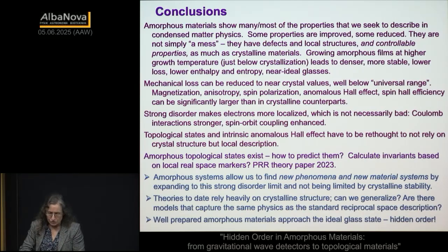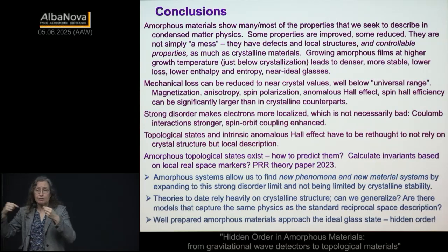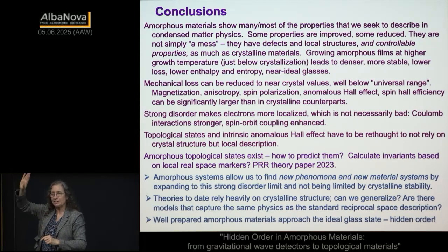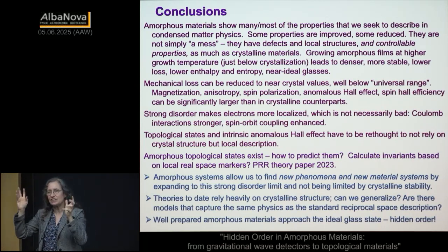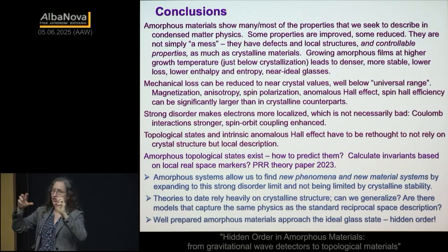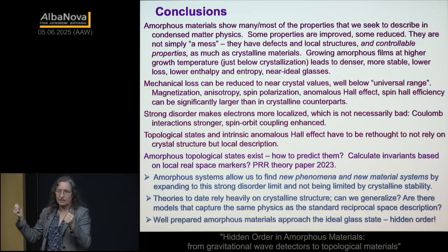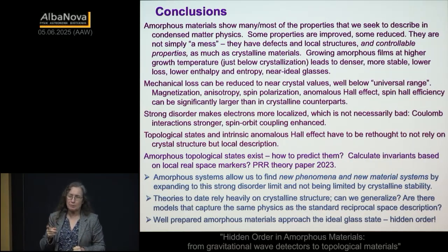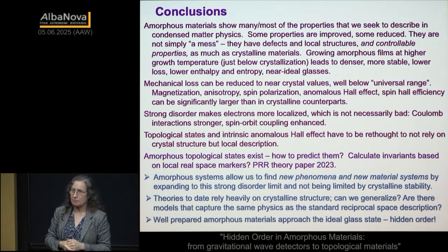If you grow at low temperatures, we've actually just recently coined a new word, which is substable. By vapor deposition, if you grow at low temperatures, which is starting to get close to your diffusion limited aggregation limit, you're higher in the energy landscape. You get caught somewhere up here, which means you're less stable. So you have less enthalpy to release when you go through the glass transition. And being higher in the energy landscape also makes it more likely to crystallize. It's like it's got a lot of energy trapped in the structure, and so it's more likely to crystallize and things like that. So the crystallization is a nucleation thing and kind of competes with all of this. But you're not wrong about the diffusion limited aggregation. The original paper that showed that was all on the limit of atoms sticking exactly where they landed. So diffusion competes with that process.